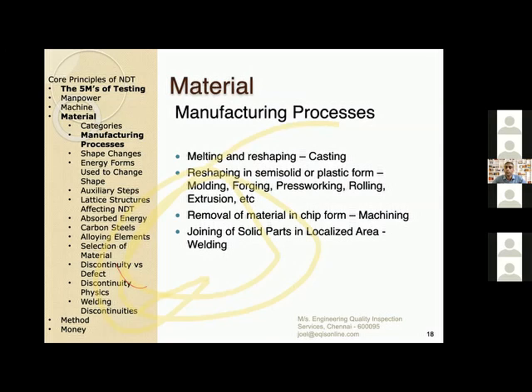And if I have to use a machining tool, then I'm going to induce a surface crack on the defect. If my run of machine is too high, if my tooling depth is too high, then I'm going to induce a heat induced stress inside the metal, which is going to develop a crack. And I also have this welding process where it's similar to casting, but it's a localized form of melting a particular place and then joining them together as a weld.